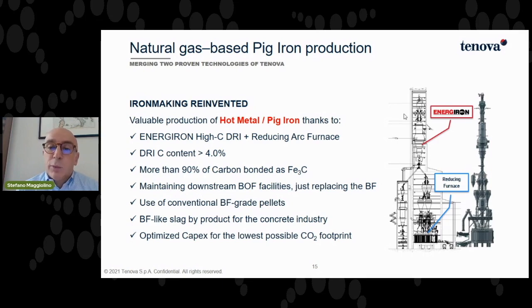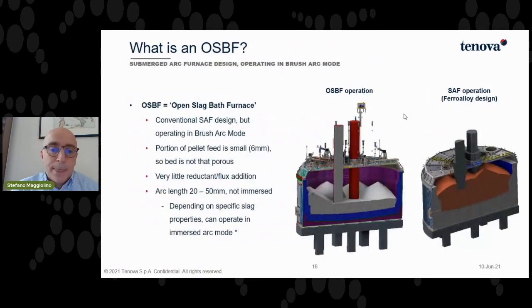First, with the system we can use blast furnace grade pellet instead of more expensive DRI grade pellet. And then we can also maintain the slag with exactly the same composition as in a blast furnace, so maintaining a side business as done in integrated mills. Everything with a cut of CO2 emission of at least 50%.